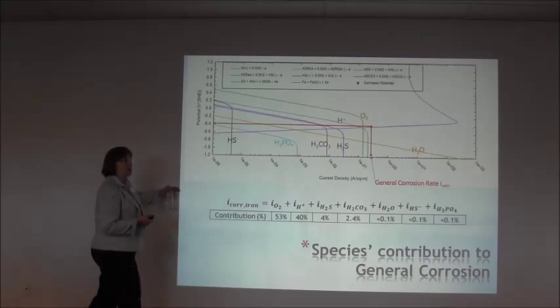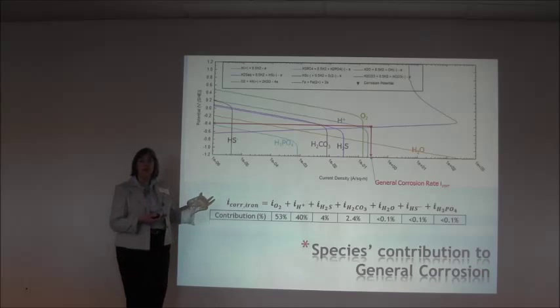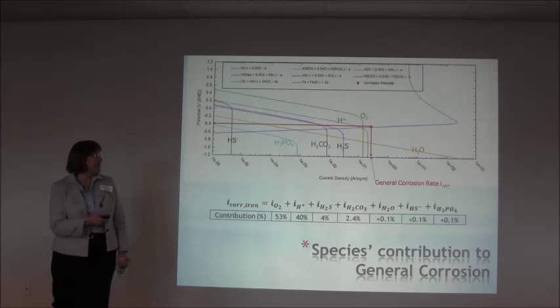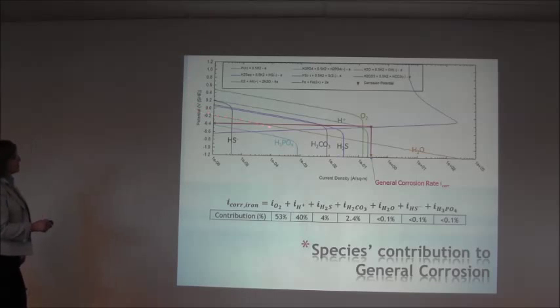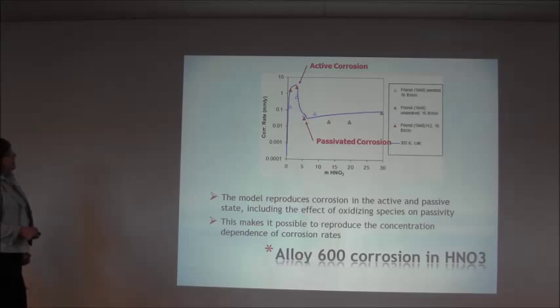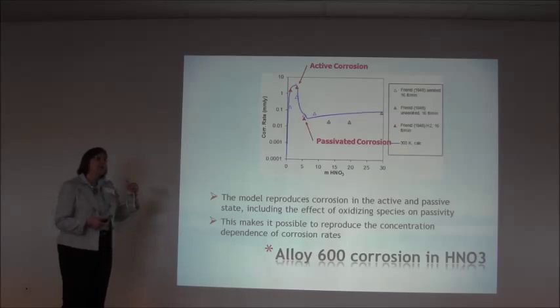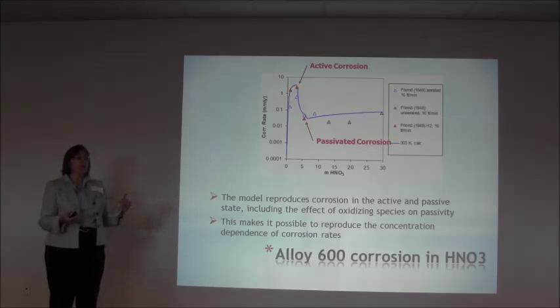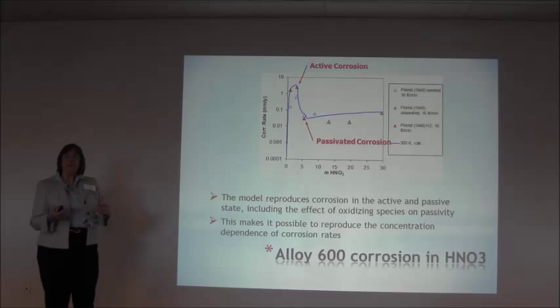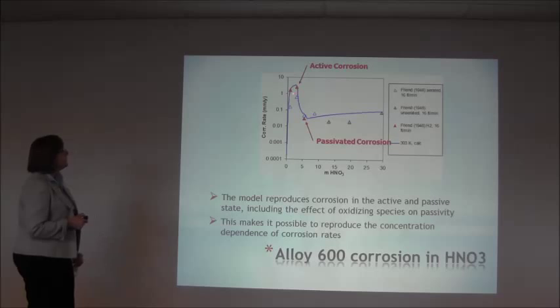Usually material scientists would produce this in the lab, but you can generate it if you have a good thermodynamic model and a kinetic model on top of it. The kinetic model is basically determining these diffusion limits. And this is just an example. From that graph, we can calculate a corrosion rate, from all those underlying species and the contributions that each one of those species gives to the corrosion model.